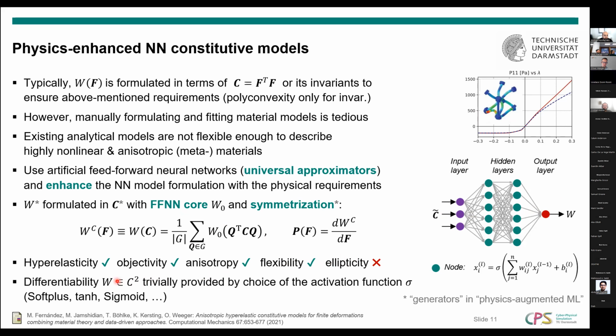It needs to be once continuously differentiable because we are always interested in the stress. And then in a finite element implementation, we also need the elasticity tensor, which is the second derivative. But this is easy to fulfill just by the right choice of activation functions. So you use something like softplus or tangent hyperbolic or sigmoid, which are at least two times continuously differentiable functions.